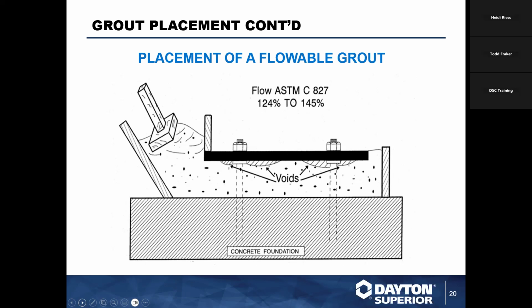Another tip is, I had a large commercial high-rise in downtown Los Angeles, and the grout was segregating like crazy and not coming up to compressive strength. The steel structure was transferring all its vibration down through the columns, down to the base plates that we were attempting to grout. Well, guess what? With all that vibration going on, it was causing the grout to segregate and flatten out, and we had to cease all activity on the building, welding, plumbing, all of it, in order to get those columns quiet while we grouted in the structure.